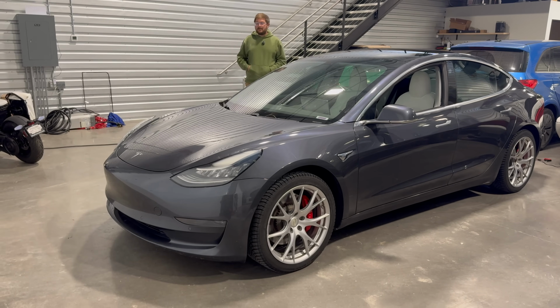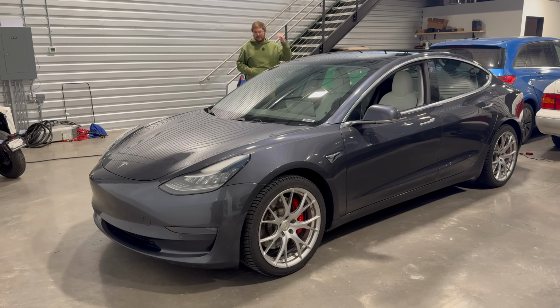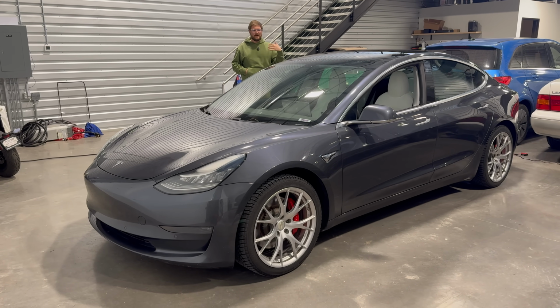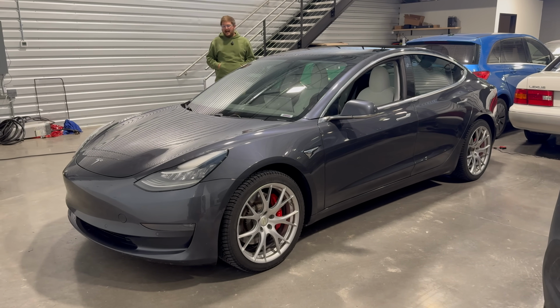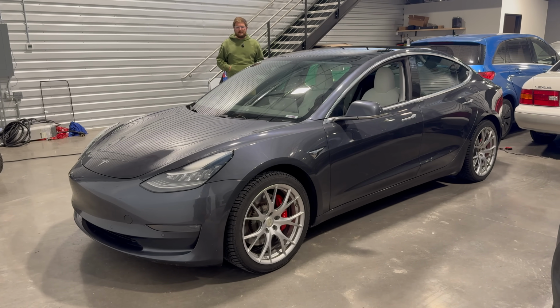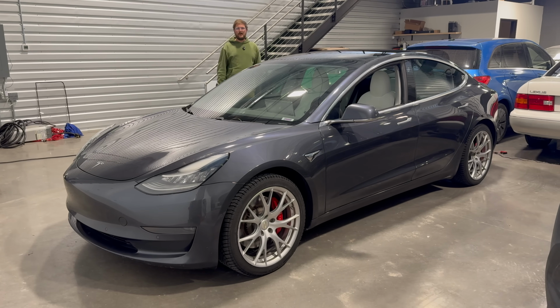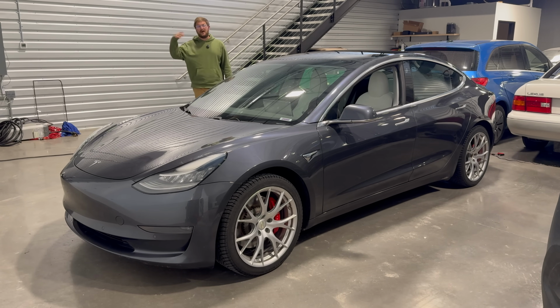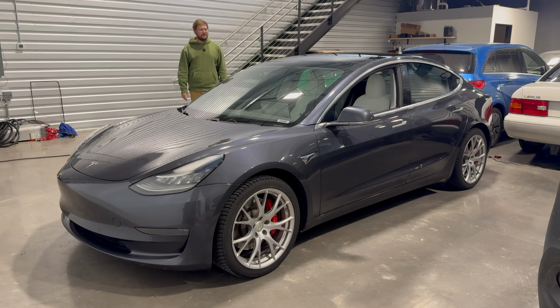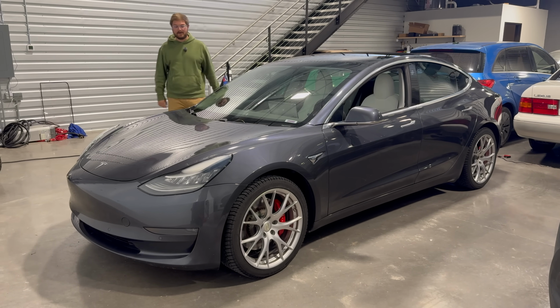And there you go. That's the performance on this particular car. So after 150,000 miles, we've lost about 19% capacity. It feels a bit high. It's definitely noticeable at this point. It sucks. There's no way around it. I'm sure if we were even gentler on the car and it just sat at very low state of charge for a long time, we would be at maybe 12% capacity loss at this point. But still, considering all the hard usage this thing has had, I think it's totally acceptable.